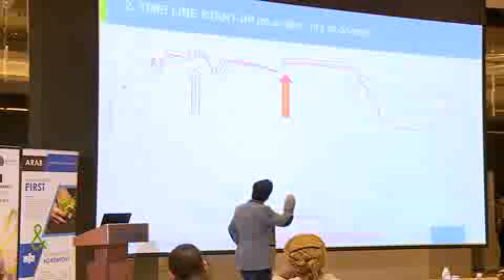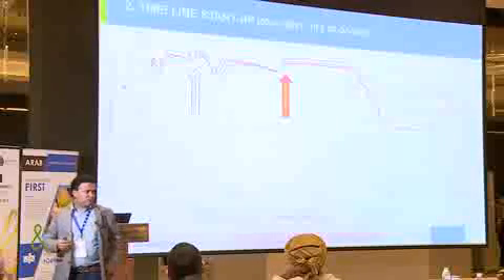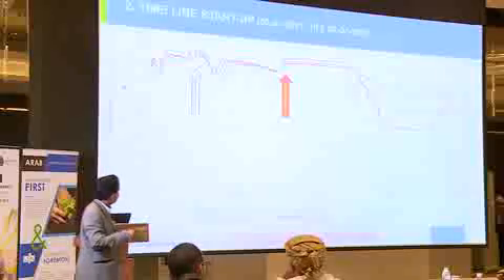You see, they ran it till about 22 hours. At the start, they did not have the usual color of the product, but very brownish. And after about 22 hours, so this is almost 1 day, they had a leak in the reactor. Due to that, they had to stop production, drain the synthesis, and look for the problem.